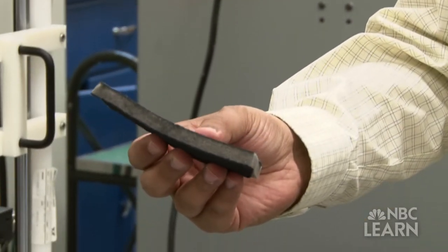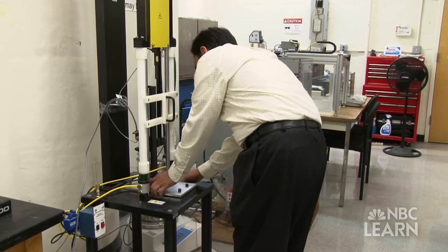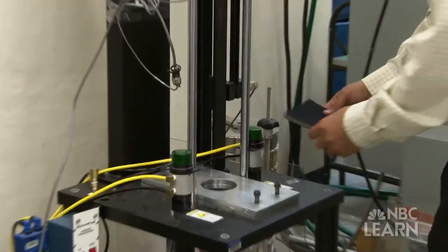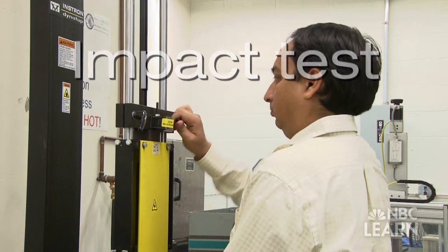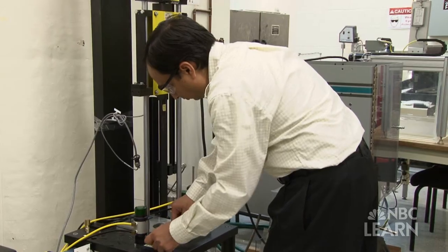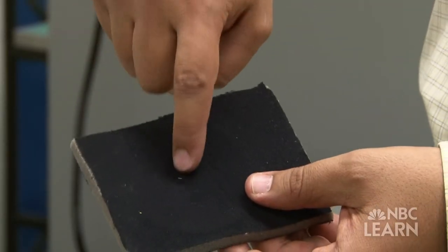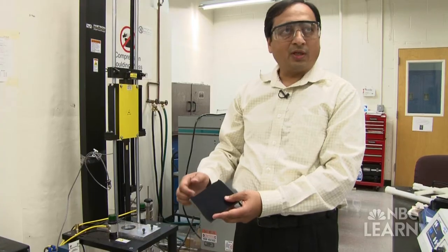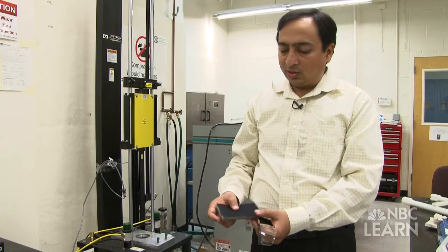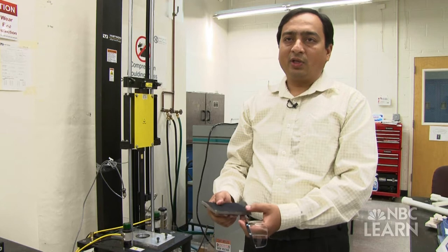Gupta's research focuses on testing the middle layer of the helmet, the rigid foam, and the testing methods are both fast and loud. During an impact test, a loaded weight is dropped from a set height onto the foam. The foam is then examined to see if the materials were able to sustain the impact. The cells have been crushed at the location of the impact, and visually this damage is very difficult to see. So this is one of the reasons that manufacturers say that after every impact, you need to get a new helmet.